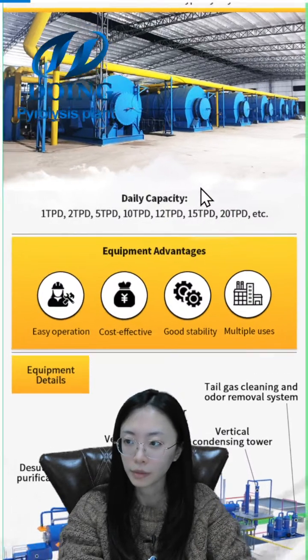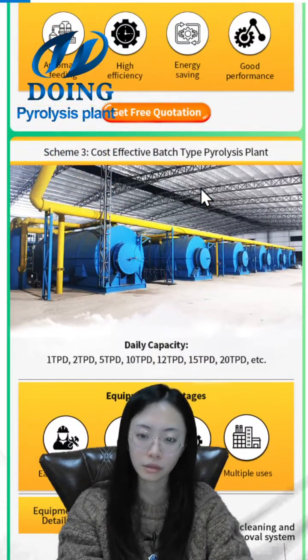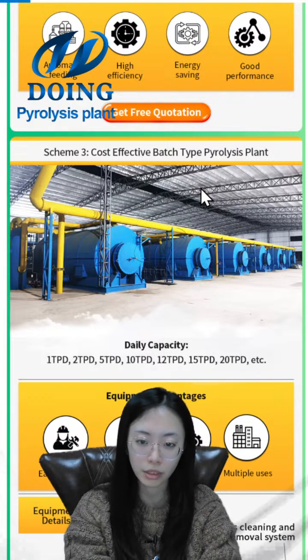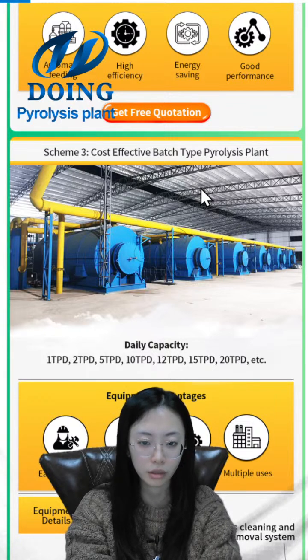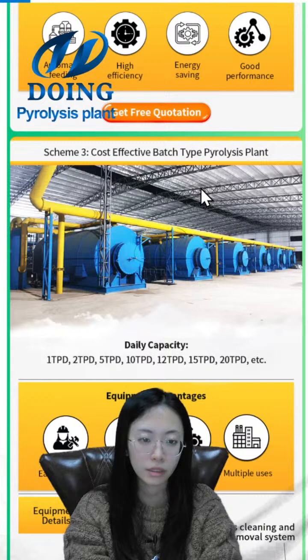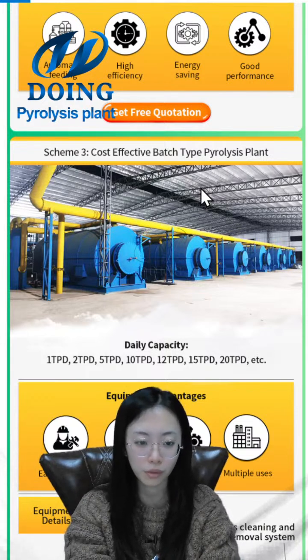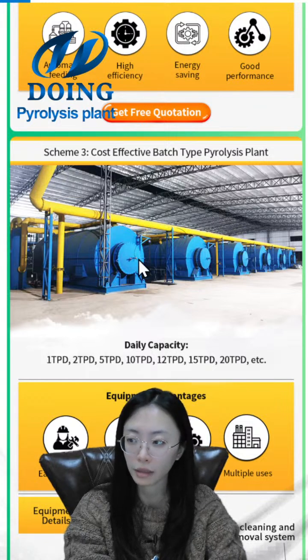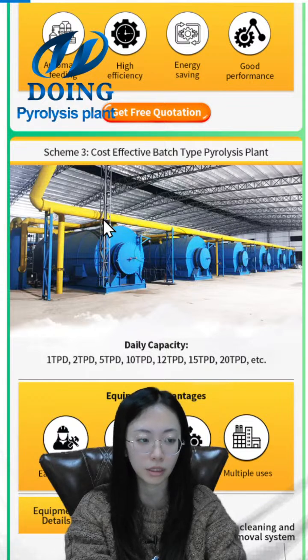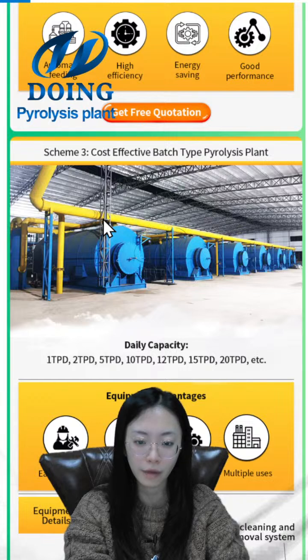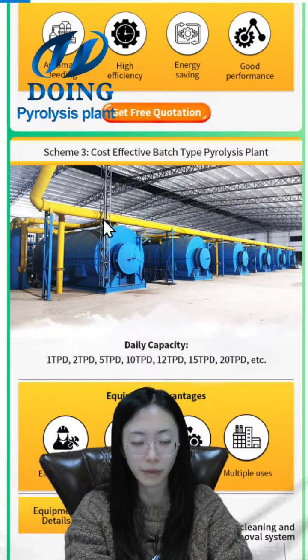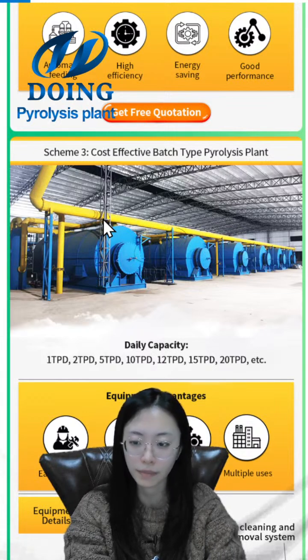But the batch type, compared with the semi-continuous and fully continuous, has some limitations. It needs to discharge carbon black at a very low temperature, lower than 100 degrees. So it's a waste of time to cool down the reactor. If we don't have the cooling system, we may need more than 10 hours. If we have the cooling system, we may need 5 or 6 hours to cool down the reactor. Compared with the semi-continuous, they can extract the carbon black at high temperature. So the batch type, we can get one batch for 1 day, and the semi-continuous one is 3 batches for 2 days. That is the difference.